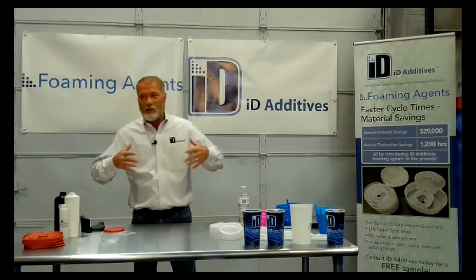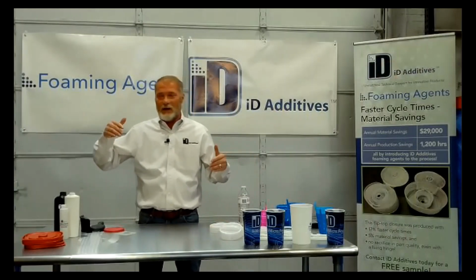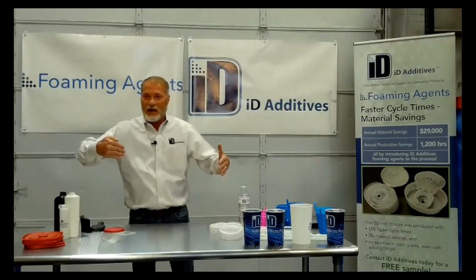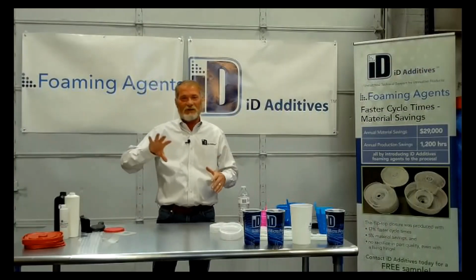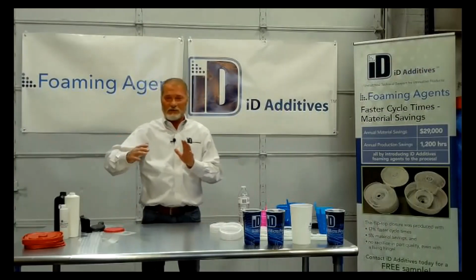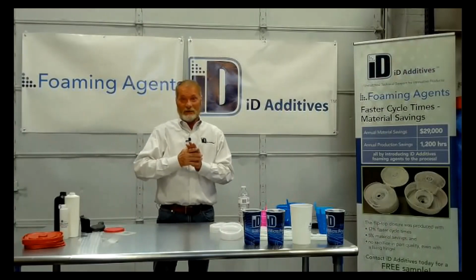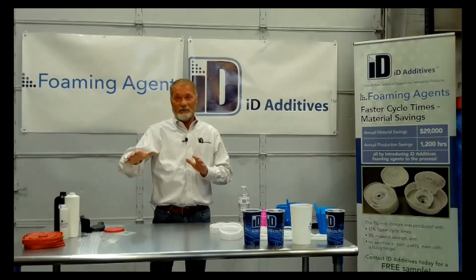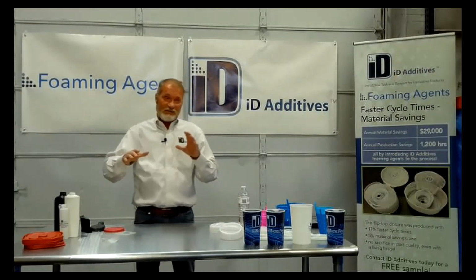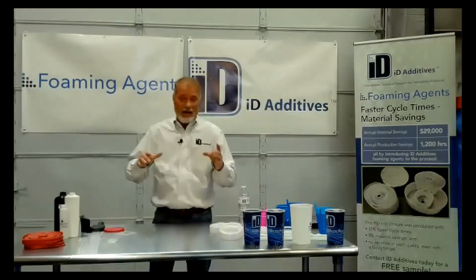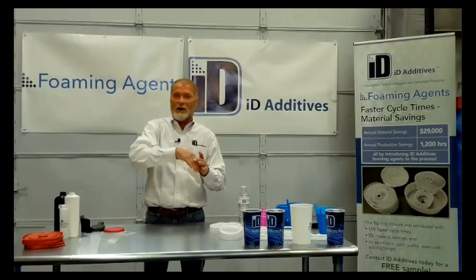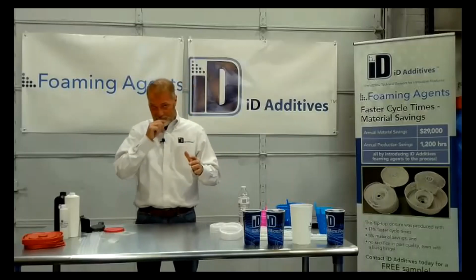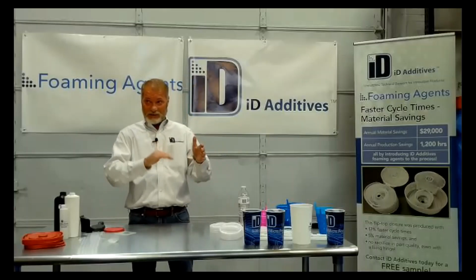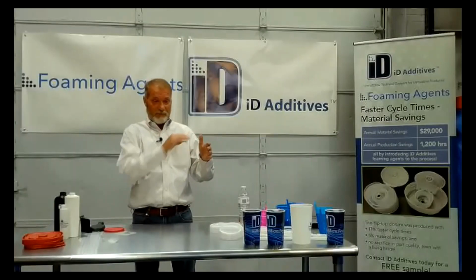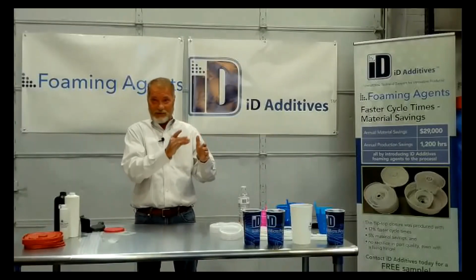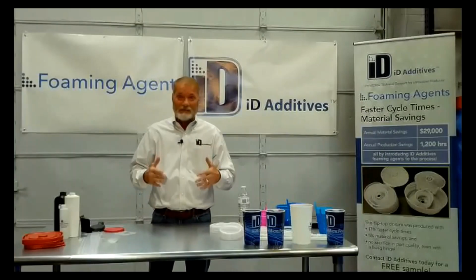The foam's flowing, right? So if there's a poor vent, it's actually going to add pressure to the foam. It's not going to push that air out of the mold. So it's literally going to pack the foam out as it's going to the end. And the other side of this cap, you got foam going all the way to the bottom. It looks great. But on the one side where you'll just see little waves like this going up in a little area like this, straight up, that's where the venting is a problem.